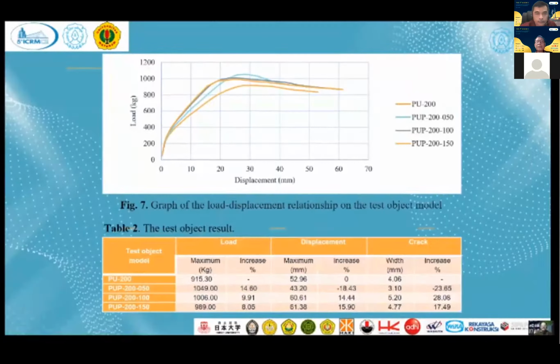Number 4, next, result and analysis. From figure 7, we can see the graph of the load displacement relationship on the test object models. And from table 2, we can see the test object results from load displacement and crack. We can see that PUP-200-050 gives the best performance in load because it can increase the load by 14.60%, and for displacement this object decreases displacement, and for cracks it also decreases the crack width.